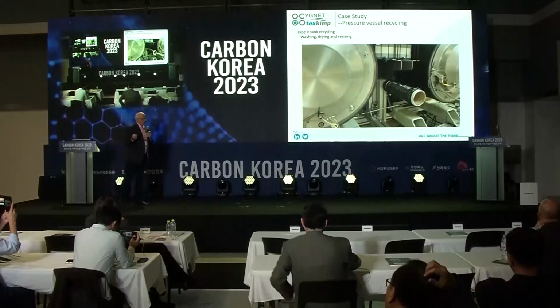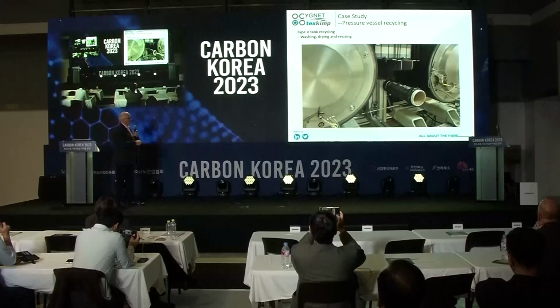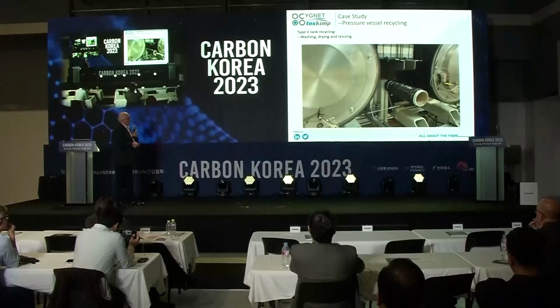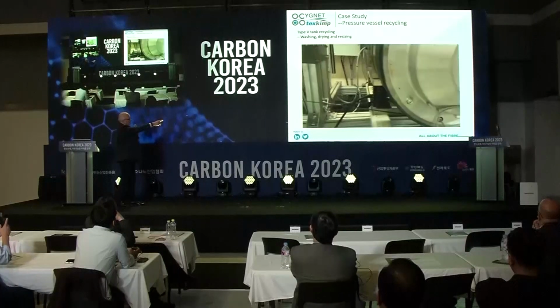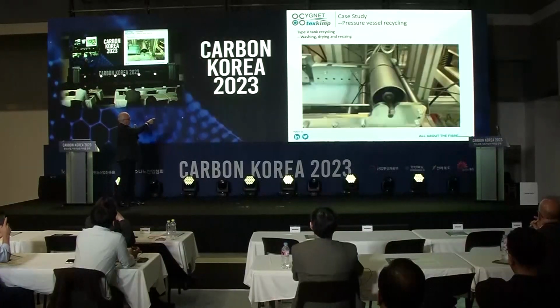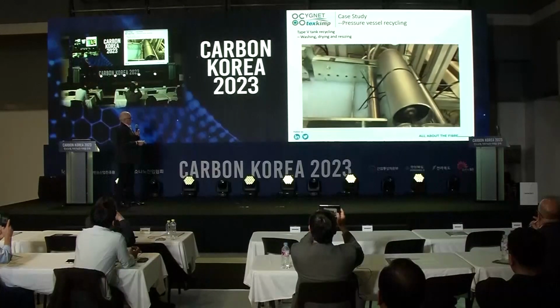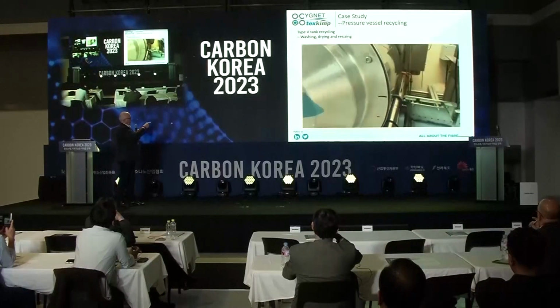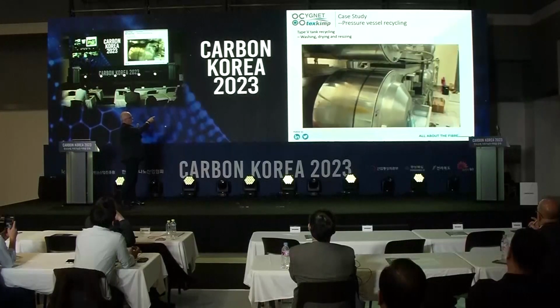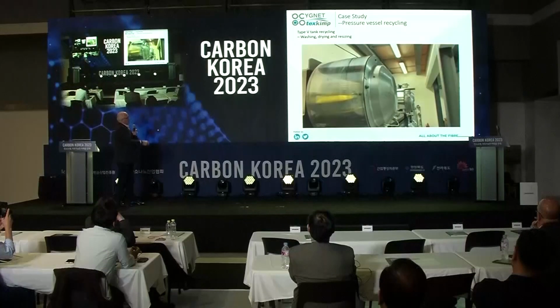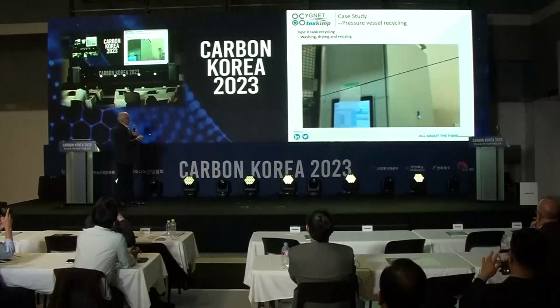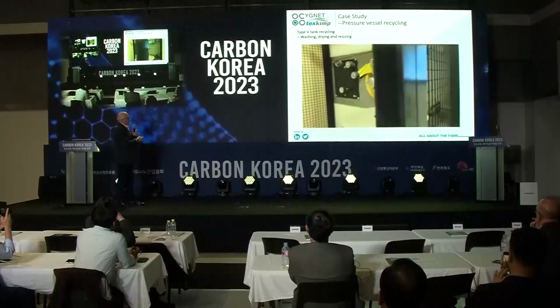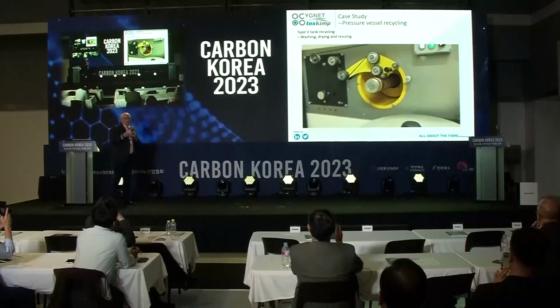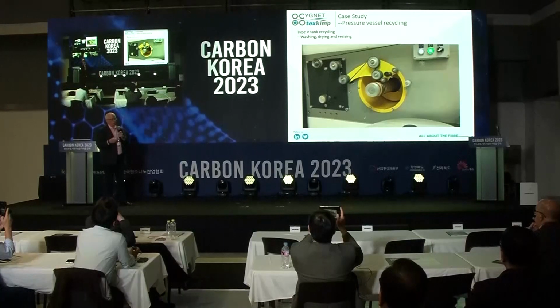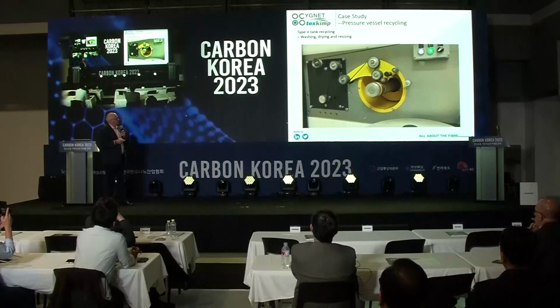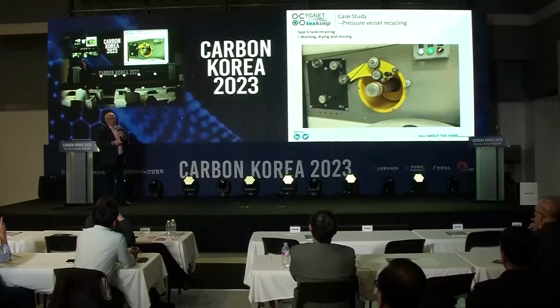And we talked about size. Well, we rigged something up on part of our machinery in the R&D department. And you can see here, this is recovered carbon fiber being washed, and then size is reapplied. You can't see it, it's underneath. Then dried, and then collected onto bobbins again for reuse. So again, this issue of size is still something that's predominantly of concern in the industry. We're looking at the possibilities there of what we can do.